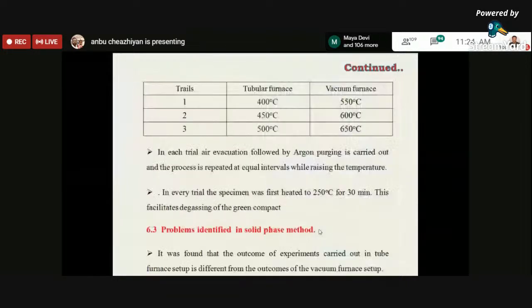Okay, here three trials have been carried out. Each and every trial has been carried out at a different temperature, one in the tubular furnace and one in the vacuum furnace. In the tubular furnace, first we went for 400 degrees centigrade, next 450 degrees centigrade, and finally 500 degrees centigrade. And in the vacuum furnace, we increased the temperature to 550 degrees centigrade, 600 degrees centigrade, and 650 degrees centigrade.